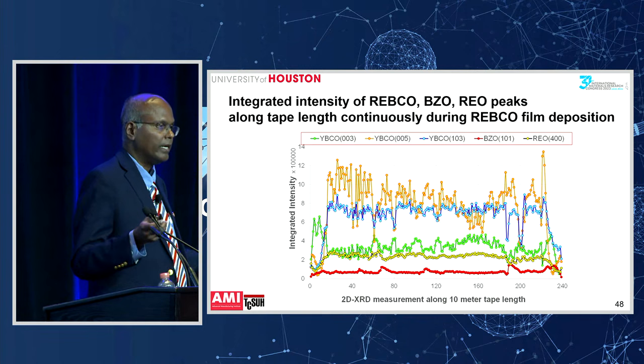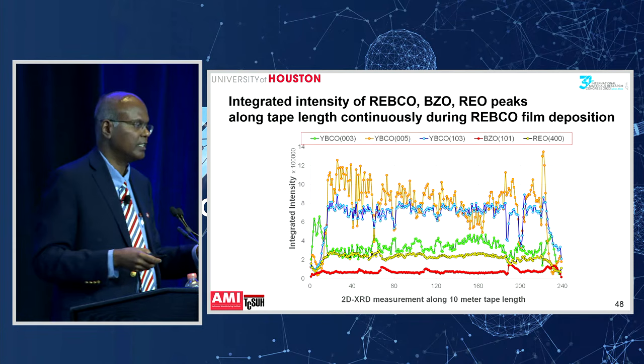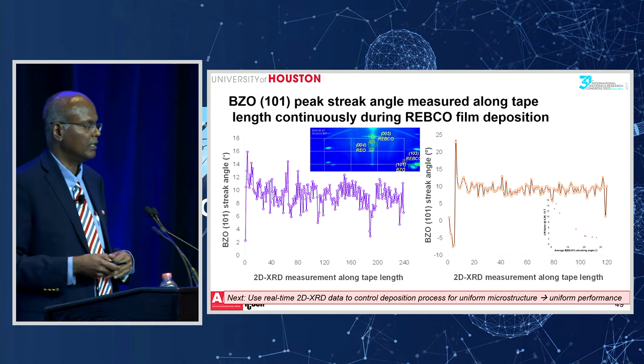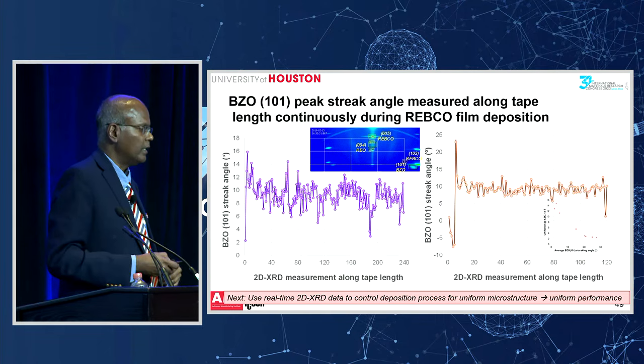You can look at the intensity of various peaks, you can look at the spread of the various peaks, you can look at the position of the various peaks, and then also the angle, right? The streaking angle I told you about between the barium zirconate and the REBCO. So everything can be monitored as you're making the tape. That really helps you to control the process much better than what's done now.